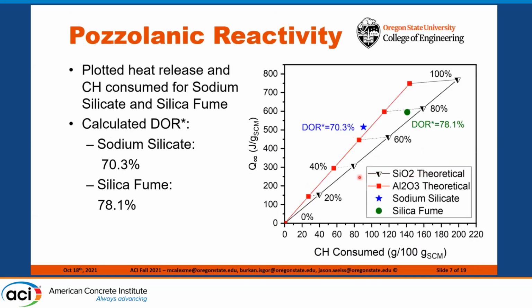When calculating and plotting our results on the PRT graph, the sodium silicate shows a 70.3% degree of reactivity compared to silica fume at 78.1%. These results are somewhat close, and the difference in degree of reactivity can possibly be explained by the silica fume being significantly more fine than sodium silicate.